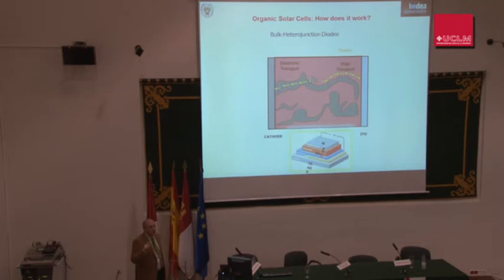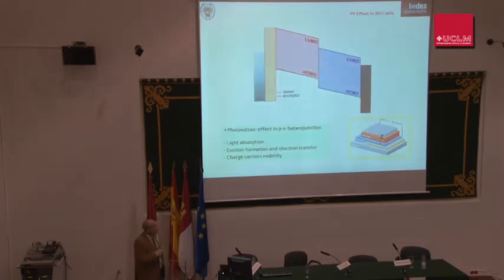So if we go one step further and want to explain this situation in more detail, considering the electronic properties, have a look at this one. You have the electrodes, this is the donor, that means the HOMO is higher in energy. This is the acceptor, that means the LUMO is lower in energy. When light irradiates, it promotes one electron from the HOMO to the LUMO, and this is the exciton. The exciton has to move to the interface, and just at the interface the charge separation occurs.